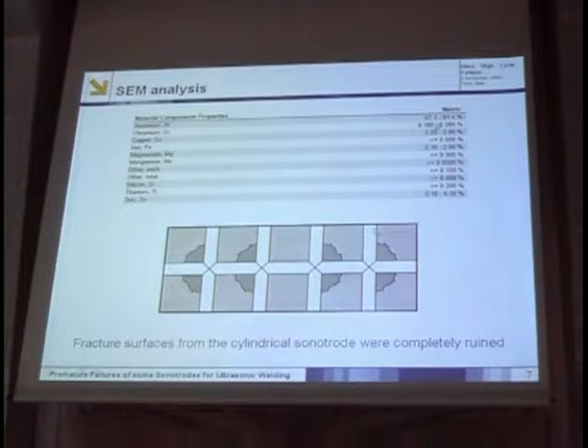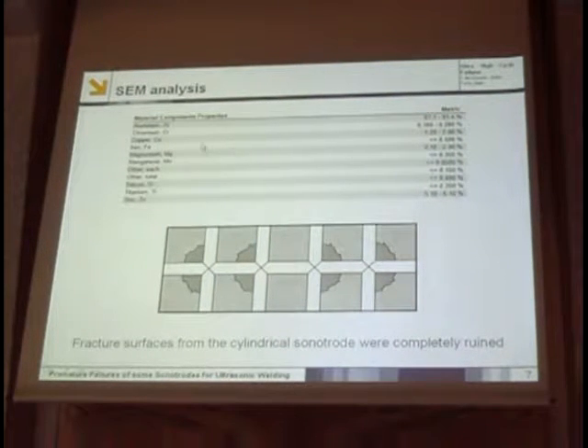Here I have reported the usual metallurgical chemical composition of the ergal, the 7075 aluminum alloy, as reported from the ASTM normative. Here there is a schematic of all the cracks we found. It's very strange and interesting. I think that there is a perfect symmetry in the development of these cracks. So perhaps there was an influence of the mode vibrations of this object during service that developed cracks in particular positions, locations in the web.